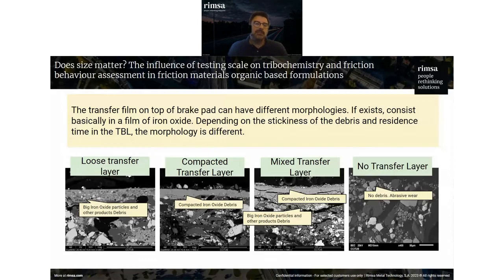Three of them are based on iron oxide, basically. This iron oxide usually comes from the rotor, from the oxidation of the rotor, and then it builds up this transfer film, and we can find what we call the loose transfer film, with big particles of iron oxide and other debris that may come from the pad. We have what we call the compacted transfer film, so it is more iron oxide, very small nanometric iron oxide debris, with a very long residence time in the third body layer, and that are stacked here.